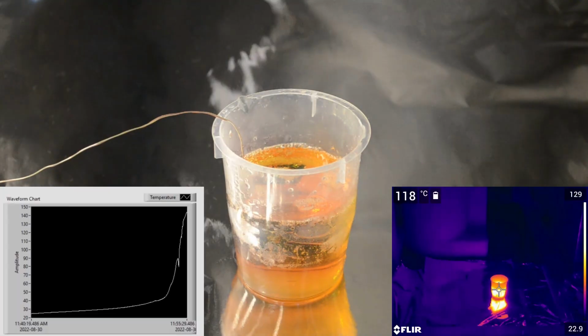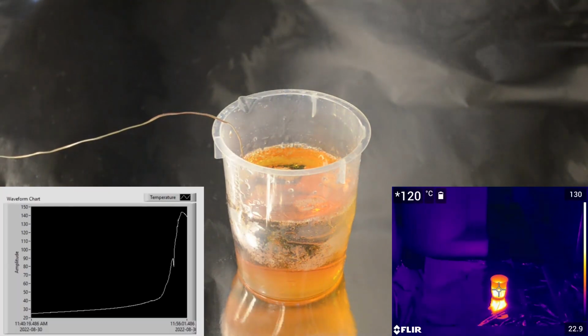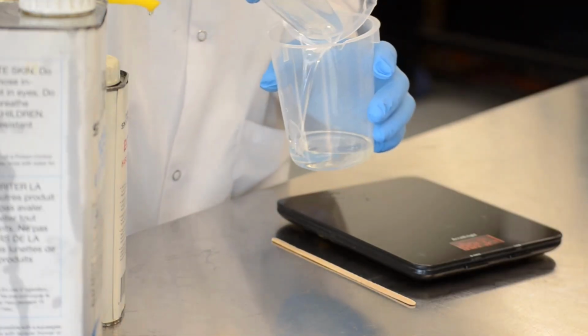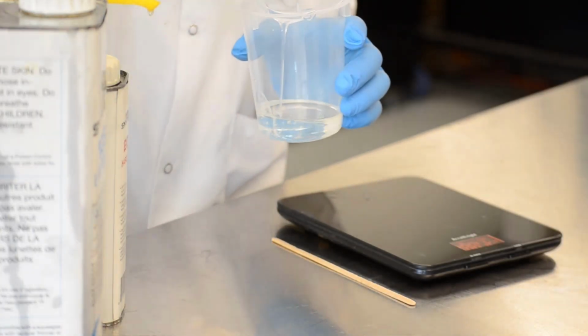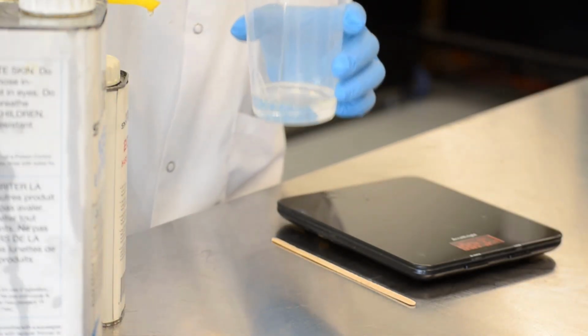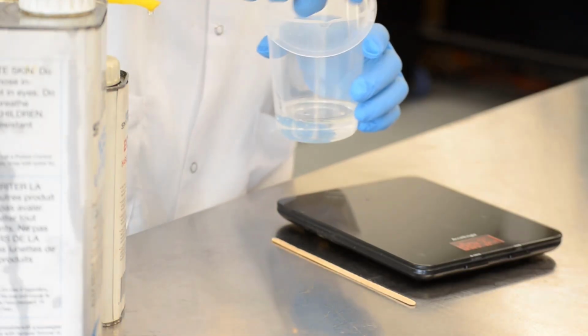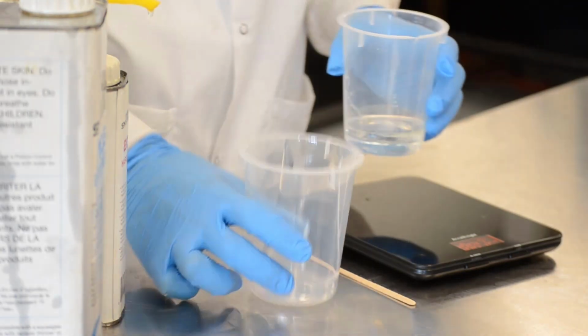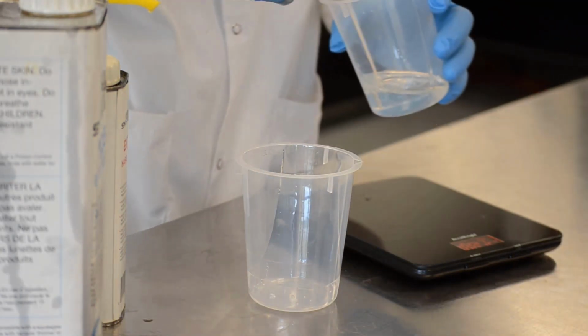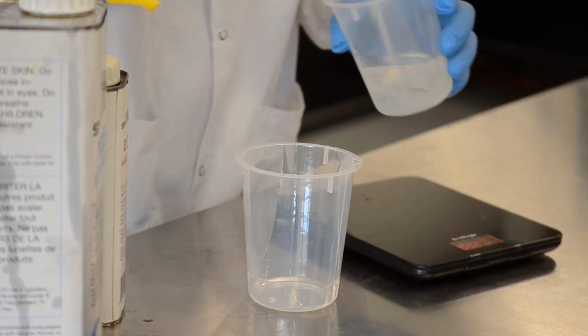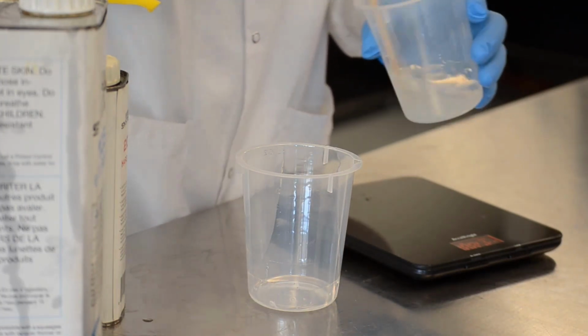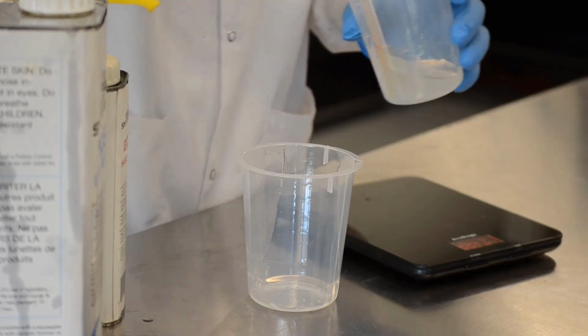It is advisable to mix fast-curing resins only in small quantities at a time. The ratio of 2 components is specified by the manufacturer, and deviations from the recommended ratio can have an effect on properties. A scale is commonly used for accurate measurements of the 2 components. If mixing by hand, a container with flat sides and bottom and a mixing tool that can scrape the sides and the bottom of the container can ensure the components are fully mixed.